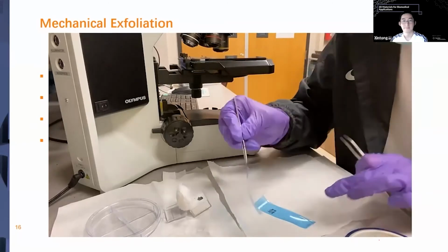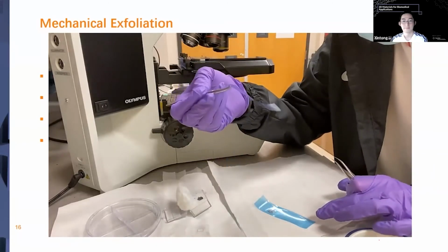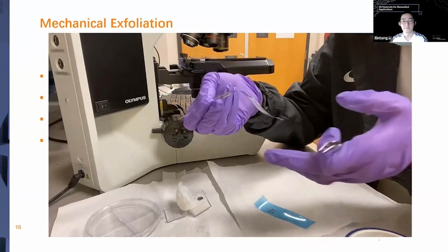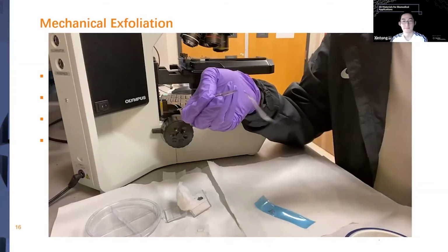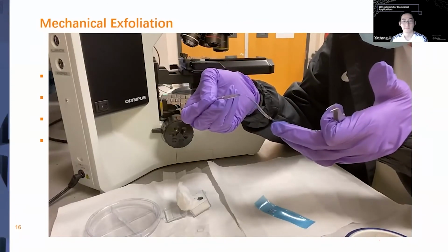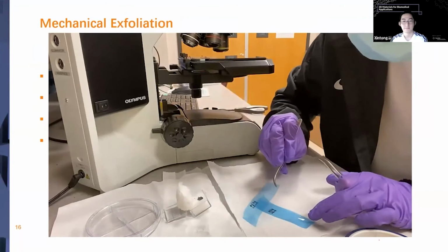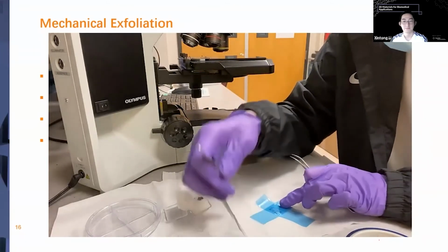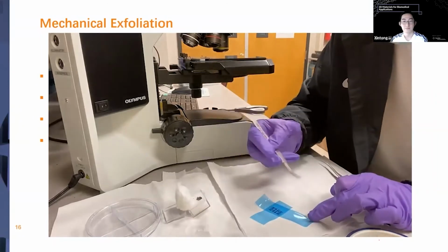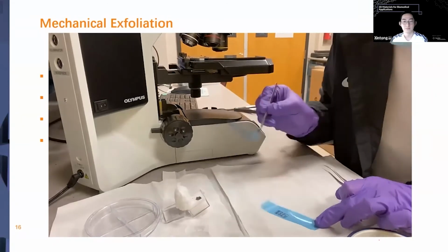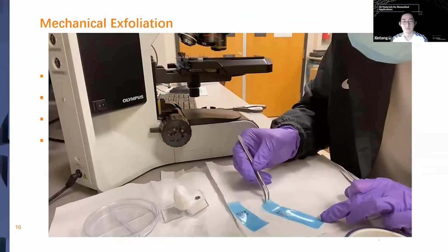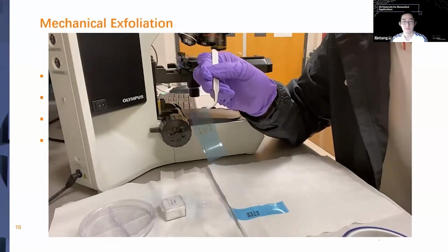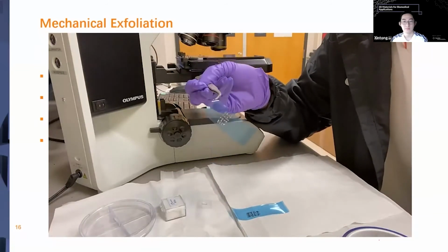It's still a little bit thick. You can tell the thickness of this layered material on the tape by examining its reflection under the light. Right now it still looks a little bit shiny, so I think probably one more time. Okay, now it's better. Then we got the 2D material on the tape that looks like this, right?